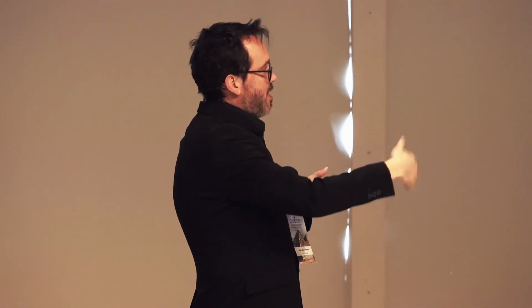And then the shapes. The shapes actually we extract by using computer tomography. So basically we use computer tomography of the electrodes, okay? If you use micro computer tomography, you will not see the carbon and binder. It is impossible to see, but however you will see very well where the active material particles are located. And then you can see very well the shapes of these active material particles. So then what we do is we extract these shapes, and we reconstruct the shapes in the computer by using a collection of spherical primary particles that we embed in the real shapes. And then we apply our force fields and so on to simulate the slurry, drying, and calendaring.